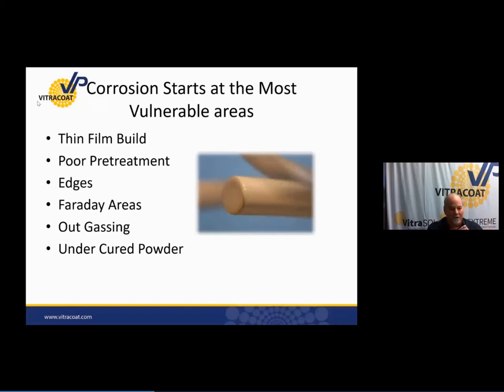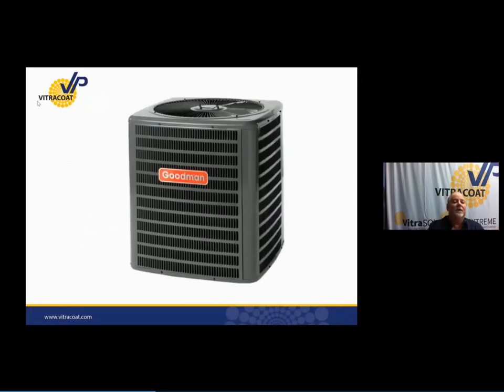And in every part that you make, your most vulnerable area can be, in many cases, your edge, not being tested on a panel. As I look at this HVAC unit and you look at the flat areas on the corners, those are probably going to perform very well and similarly to a panel, but the louvers are going to be my most vulnerable area because it's hard to build film on an edge unless that edge is rounded or sanded or prepared well. And with the abundance of louvers here, that would be just totally too difficult, too time consuming.